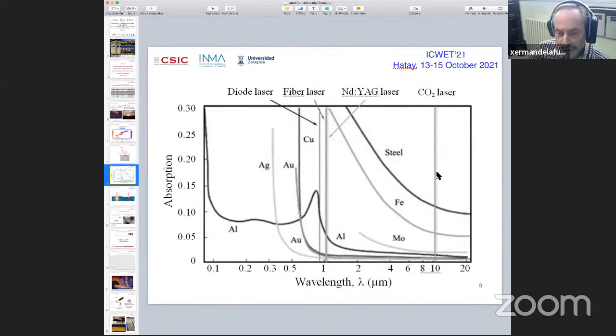CO2 lasers were traditionally used a few decades ago, after the invention of the laser, because they were the ones available with the highest power and most developed at that time. Solid state lasers and fiber lasers were still not sufficiently developed. So you can see the CO2 laser. This is absorption going upwards. The absorption of steel is much higher than iron, molybdenum, aluminum, or even noble metals like gold or silver. And so a CO2 laser is still being used with metals for different applications, even surface modification,